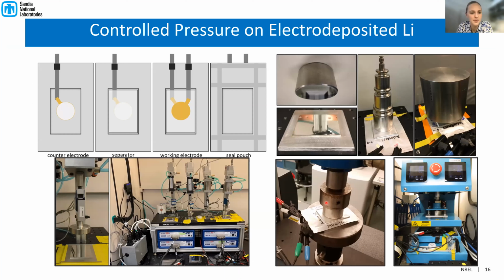So in Katie Harrison's lab, she set up these pouch cells so that she had a lithium counter electrode on the bottom. Then she would enclose a separator with a working electrode, just a copper current collector, on the top. And then she would seal that all inside of a pouch cell, fill the separator with electrolyte, and then seal it up. So with these mirror finish platens, she could either use just weights to control the pressure, or she could use load frames that had feedback control so that they would keep the pressure consistent as the lithium plated and stripped, because you can imagine there's a lot of volume change as you plate and strip the lithium inside the cell.